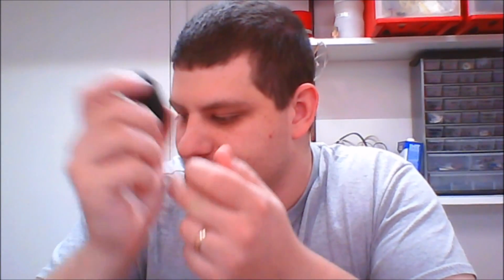This is what we learned today. We learned that 3D printed parts in PLA and ABS are not airtight whatsoever by themselves. We learned that TPU is better, especially on the sides, but for some reason in some areas that I can't explain, it leaks more. We learned that cold vapor smoothing, while it does make it shiny and smooth, does not get rid of the porosity of a part. But we learned that using an acetone and ABS slurry or a fiberglass resin to seal a part does make it airtight, or can make it airtight if you do a good enough job. You also learned that you can use NPT threads in a 3D printed part, but you really want to use something like a Teflon tape or a plumber's putty.